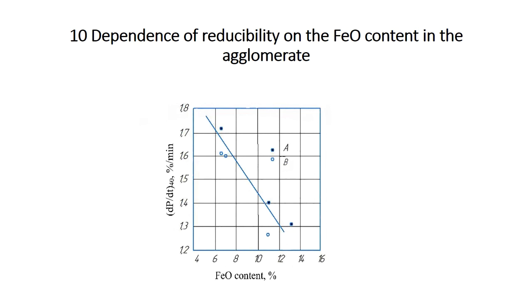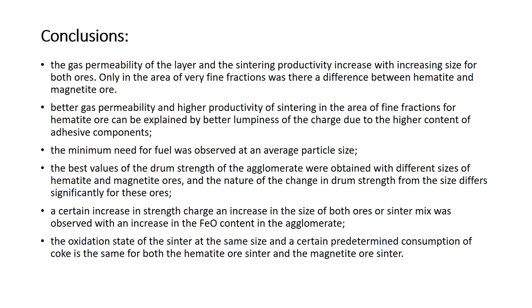Experiments on sintering artificially obtained mixtures of fractions from magnetite ore A and hematite ore B made it possible to reveal a number of features of this process depending on the grade and size of the ore. In particular, it can be concluded that the gas permeability of the layer and the sintering productivity increase with increasing size for both ores. Only in the area of very fine fractions was there a difference between hematite and magnetite ore. Better gas permeability and higher productivity of sintering in the area of fine fractions for hematite ore can be explained by better lumpiness of the charge due to the higher content of adhesive components.